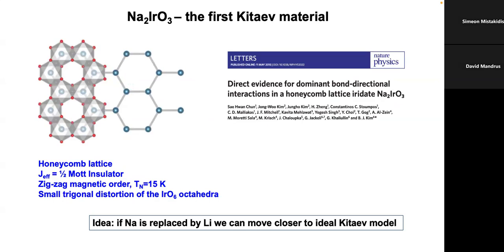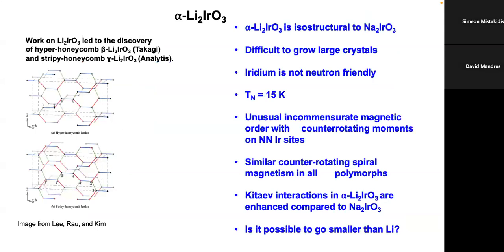And there was indeed evidence for this bond direction of Kitaev exchange. So that got people even more excited. By looking at the bond lengths and so forth, people said, okay, if we could replace sodium by lithium, we could even move closer to the Kitaev model. And they did, and it did get a little bit closer to the Kitaev model. So they made this other material, alpha lithium 2 iridium O3. It's isostructural to the sodium 2 iridium O3. But there are problems with it. It's difficult to grow big crystals. The way you want to study these materials is with neutron scattering. Iridium is not a very friendly element for neutron scattering.